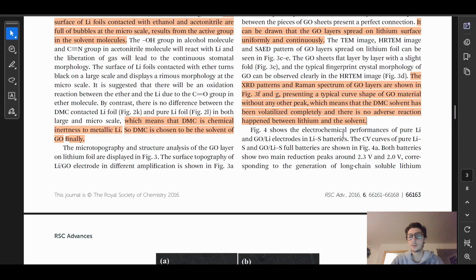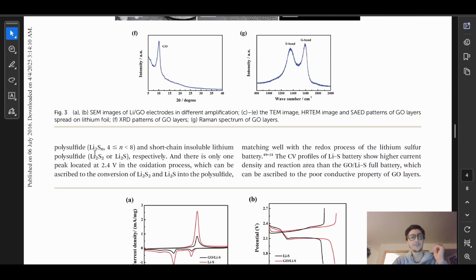Figure 4 shows the electrochemical performances of the lithium and graphene oxide lithium electrodes in lithium sulfur batteries. The CV curves of pure lithium sulfur and graphene oxide lithium sulfur full batteries are shown in figure 4A. So they're comparing just lithium sulfur batteries and this modified graphene oxide lithium sulfur battery. Both batteries show two main reduction peaks at 2.3 volts and 2 volts, corresponding to the generation of long chain soluble lithium polysulfide Li2Sn, where n is between 4 and 8, and short chain insoluble lithium polysulfide Li2S2 or Li2S, respectively.